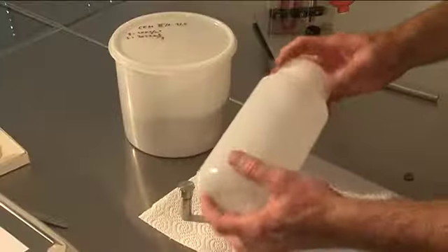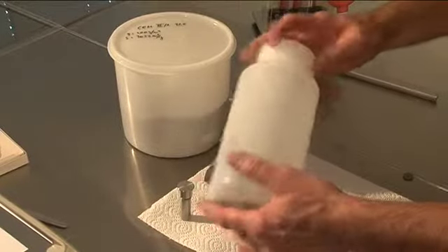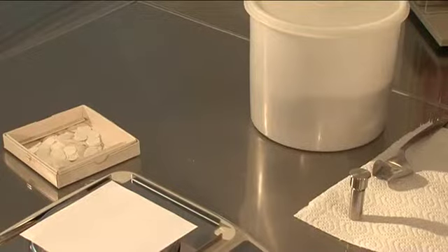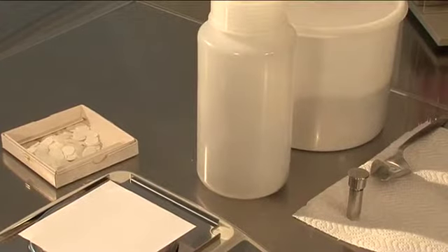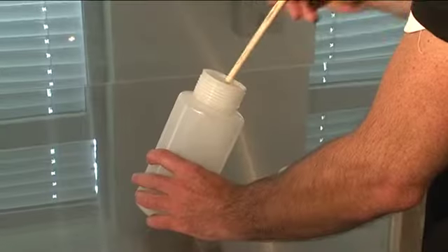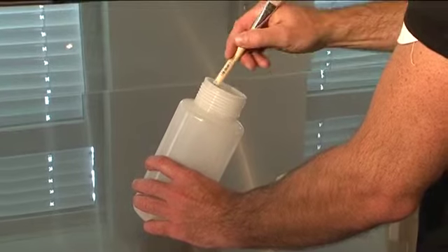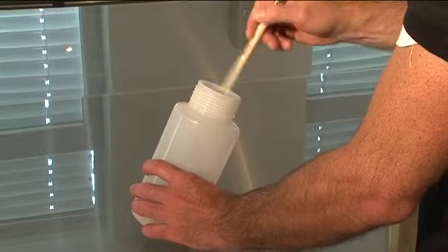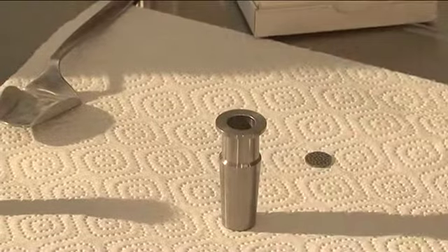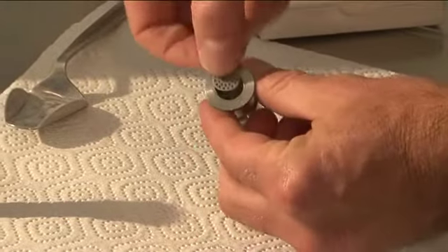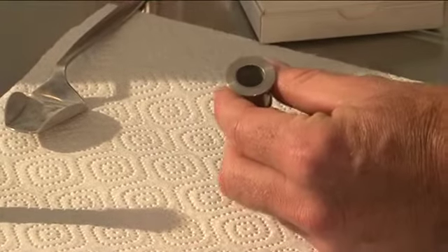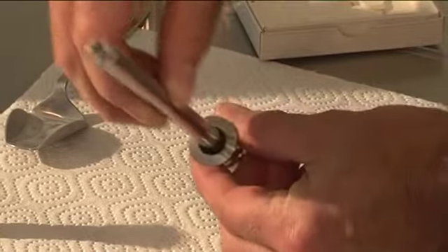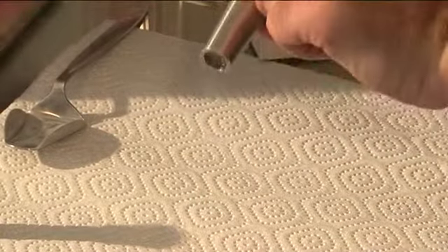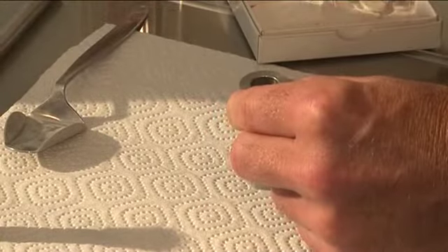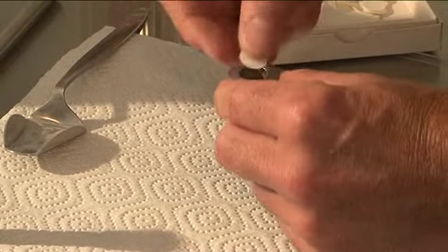It must be shaken for at least 2 minutes to dissolve any agglomerates. The bottle is then left to stand for 2 minutes. Stir the cement with a clean, dry rod in order to evenly distribute the fine particles. The perforated disc is laid on the bottom of the measuring cell and lightly pressed with a rod. Insert a filter paper disc and lightly press it onto the perforated disc with a rod.